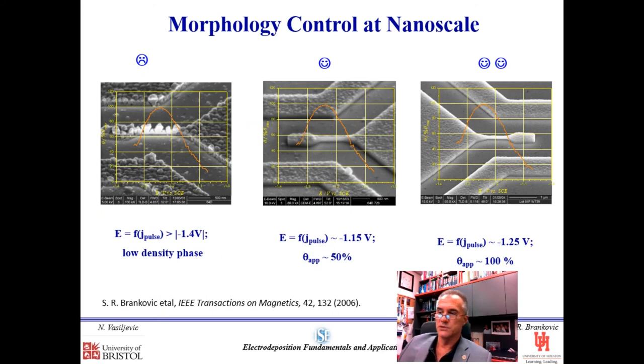And just to say a few words on the side of the nanostructures, obviously creating nanostructures where the electrode dimensions are a few tens of nanometers, creating the structure where the morphology is well controlled is not so easy anymore, because the electrode size is very small. And this is a typical example here in the deposition of magnetic pole tip structures for recording heads, where we have conditions for active adsorption which are quite different.